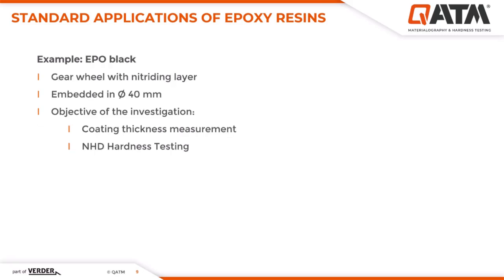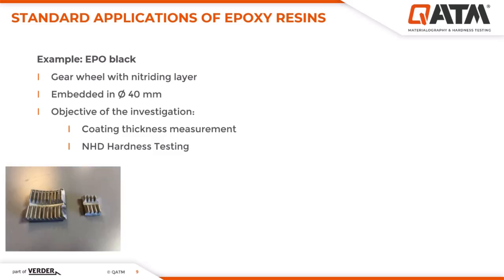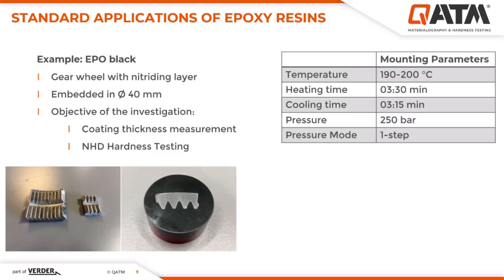Here is a standard example of an application using epoxy resin. A part of a gear wheel with nitrided layer coating was prepared and mounted in a diameter of 40 mm. The aim of the examination was to measure the thickness of the nitrided layer and to perform the NHD hardness test. This gear segment was mounted at 190 to 200 degrees, heated for 3 minutes and 30 seconds at 250 bar, and then cooled for 3 minutes and 15 seconds.